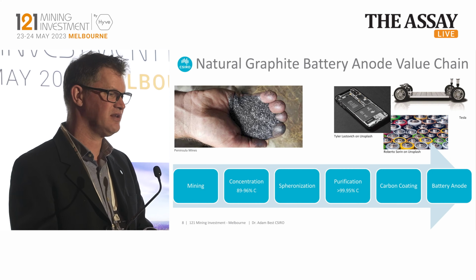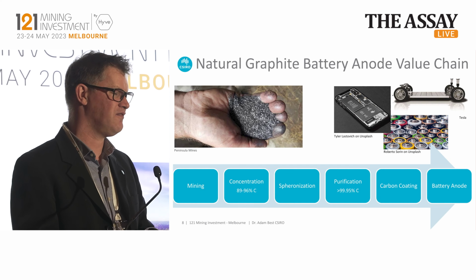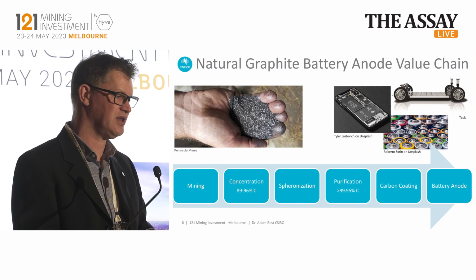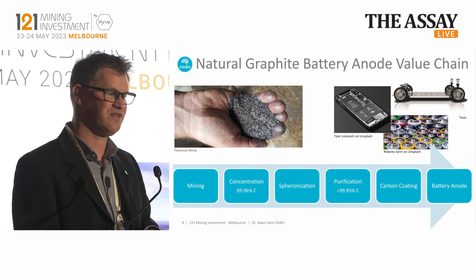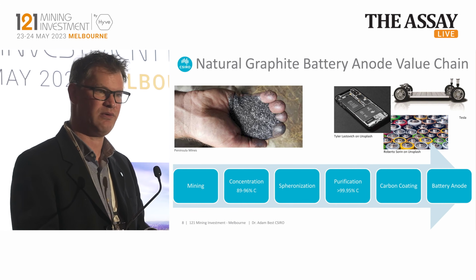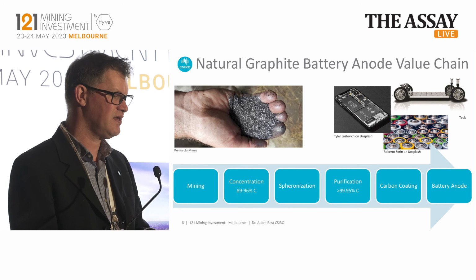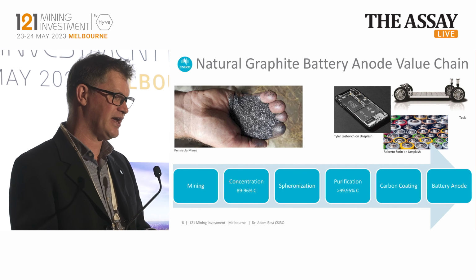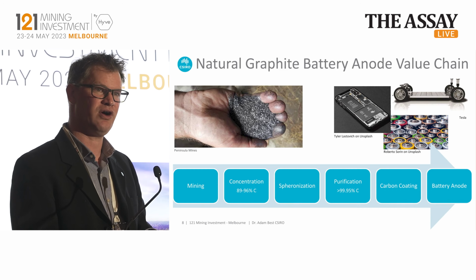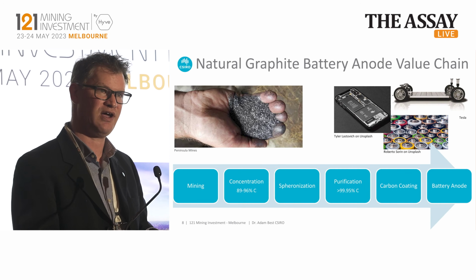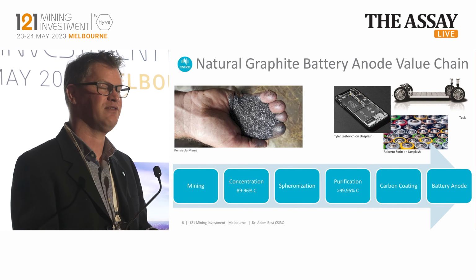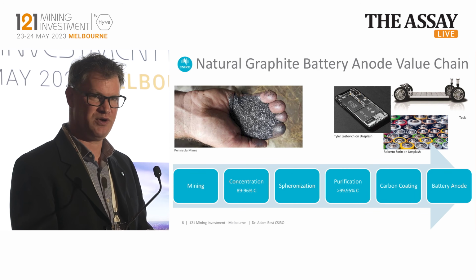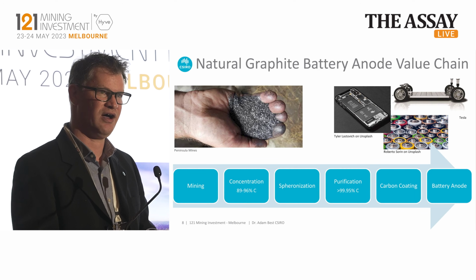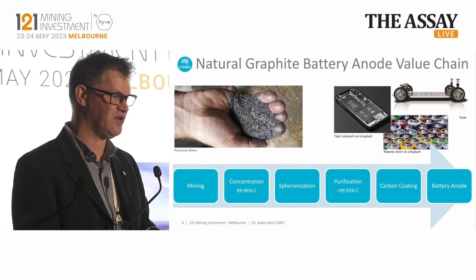So concentration occurs via crushing and flotation, which I'll go through shortly. Then we go into a process called spheronization, which is where we make small potato-shaped materials. Final stage purification, and you'll see there we're trying to get beyond 99.95% graphite. Why? Because lithium reacts with everything. You want the purest form of material you can to get the highest rechargeability in your device and the longest